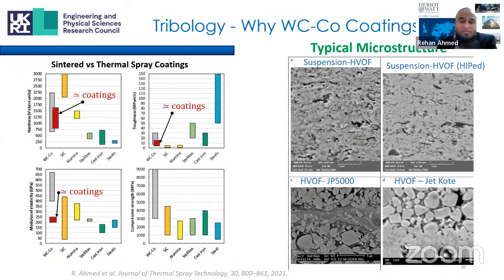For example, the Young's modulus of thermal spray coatings is roughly 1/3 of the sintered value. And similarly, fracture toughness ranges between 2 to 14, depending upon the coating process as well as the direction of fracture toughness measurements. The SEM images on the right show typical microstructure using conventional JP5000 and Jet Kote techniques, and also suspension high velocity oxyfuel in both as-sprayed and also heat treated conditions.